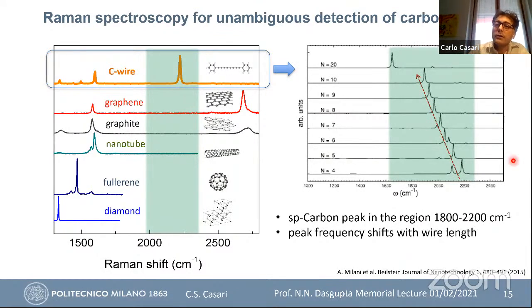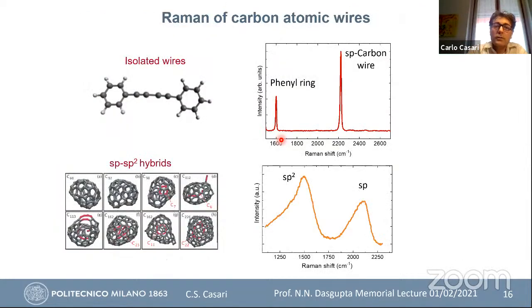More than this, the Raman peak, the main peak, shifts with the length again, because the size is able to change the vibrational properties, and so by this shift we can also distinguish different structures. This is an example. You have on top isolated wires in which we see the main sp peak and also the termination, that is the phenyl. In a mixture of sp2 and sp carbon, we can see the well-known D and G bands for sp2 amorphous carbon and sp.